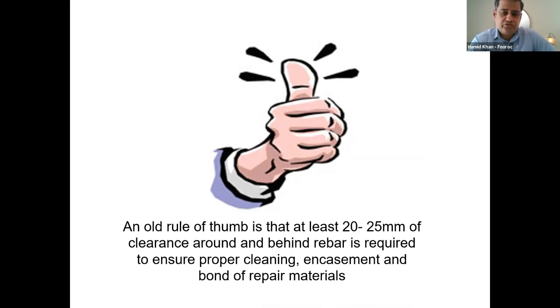But there is also a need of going back to basics. 20 to 25 millimeter behind the rebar. The standards also say that you have to keep on breaking the concrete until you reach the sound concrete. Sometimes it's not possible, and the concrete is very strong and very durable. There might be something going on inside it. In that case, new innovations and technologies are now in place. Those areas can be protected by a targeted approach, by drilling and inserting galvanic anodes.